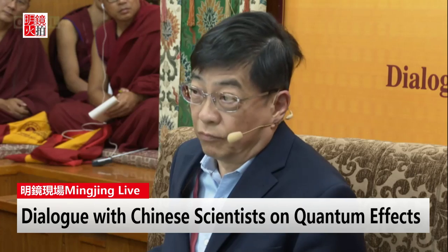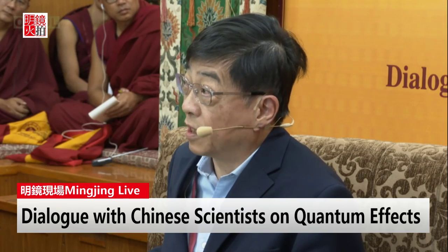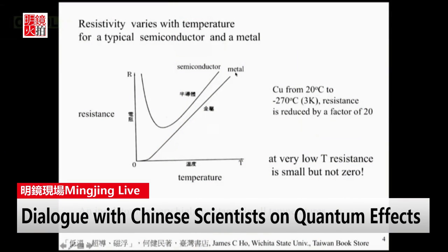The usual wire we use these days is made of copper. Copper at 20 degrees Celsius, somewhere around here, at room temperature. That's the room temperature today. Here is a little bit less than that. But then as temperature goes lower, the resistance keeps on going down. It goes down by a factor of 20, meaning divided by 20. So the conductivity increased by a factor of 20.